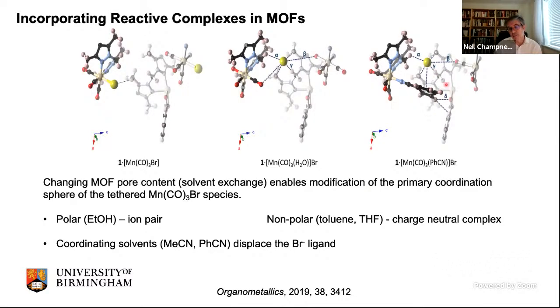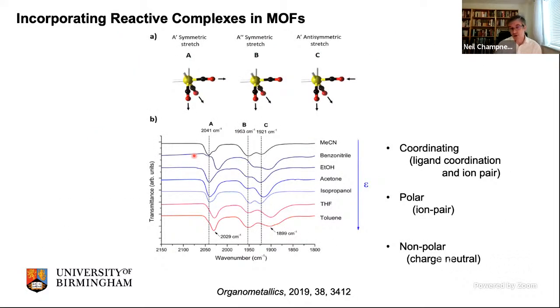Now here are the crystal structures of all the different variations on the theme that I just showed you. Here's the coordinated benzonitrile, bromide counterion. Here's the water complex. And here's where the bromide is actually bound to the manganese center. We're just changing that partly as a factor of polarity, but also as a factor of the coordinating ability of the various solvents. You can follow this by infrared spectroscopy, of course, because you have a metal carbonyl species, and you're changing the coordination environment, so you can follow this process quite easily by looking at the carbonyl bands and the different symmetries which you generate by this isomerization process.